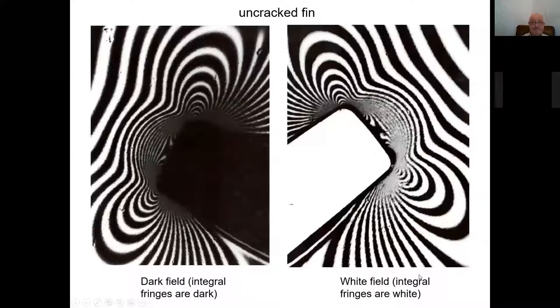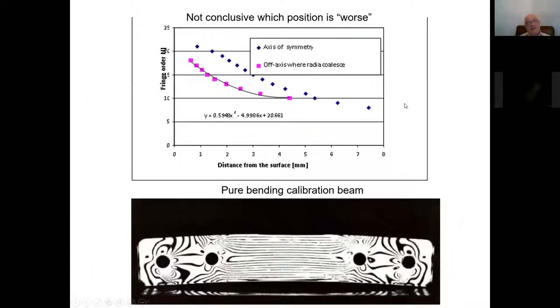So why is this important? Well, this is important because we needed to decide where it is worse to have the initial crack: in the middle or in between this radius and the other one, so in this off-axis position. Because you see here the fringes are going towards this stress raiser, which however appears here. We did some evaluation. After this evaluation, of course, you cannot go exactly at the surface. It looked like, in fact, it was about the same. So around 20 was the fringe order.